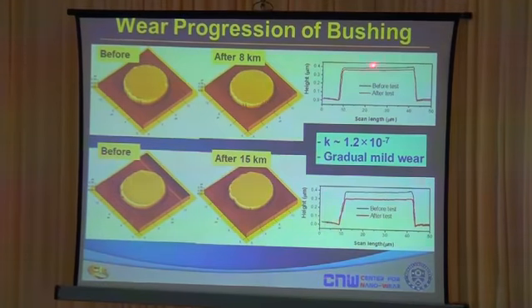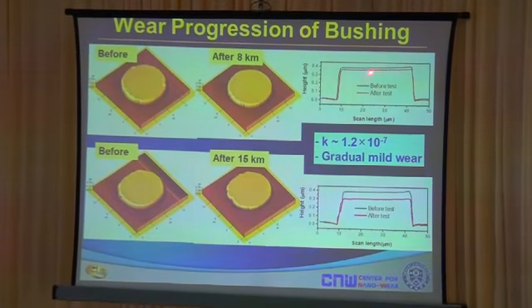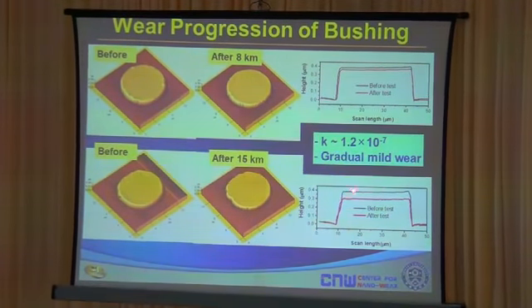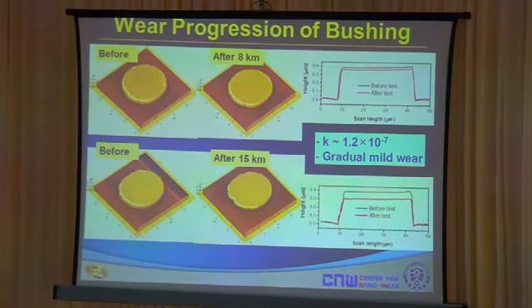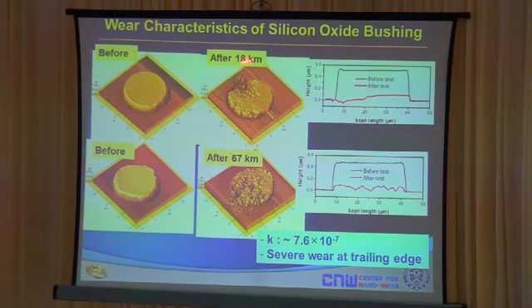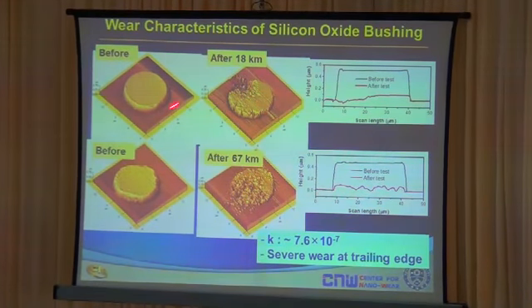This is before the experiment. That's after 8 kilometers. You can see that the specimen is worn out a little bit. After 15 kilometers, it worn out more. And by measuring the amount of wear volume, we're able to quantify the wear coefficient, and the wear coefficient is in the range of 10 to the minus 7, which is about 4 or 5 orders of magnitude smaller than that of the AFM tip. Now, if you look at the wear of the silicon oxide bushing, we fabricated silicon oxide bushings and we observed the wear.